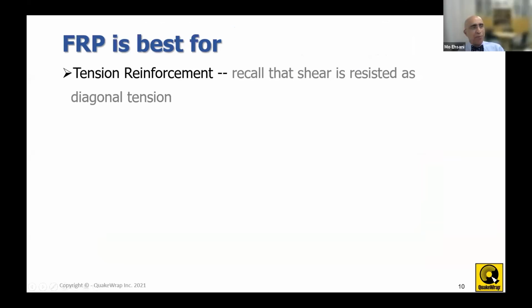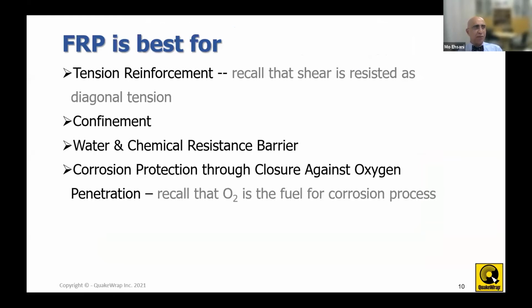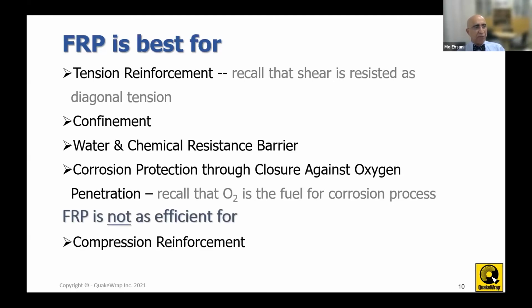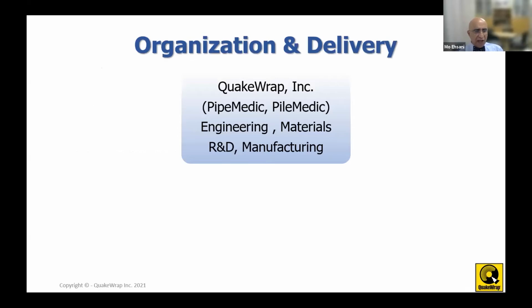But these FRP products are best for tension reinforcement. And again, realize that in concrete structures, shear is also resisted as diagonal tension. So they work with that. They're excellent for confinement, water and chemical resistant barrier. Remember that for corrosion to take place, you need oxygen present. And if you wrap your structure with a layer of FRP that does not allow oxygen or moisture to penetrate, this definitely would help stop the flow of oxygen, and it would bring the corrosion to a very low rate. What they are not so good at is for compression reinforcement, and we usually ignore their contribution to compression.